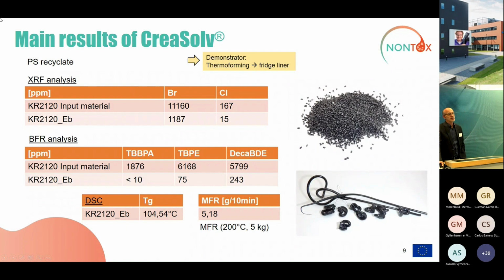Same is true for polystyrene. Again, here bromine and chlorine levels. So you see the input and the output. You see again that specific BFR analysis clearly indicates that the substances of concern are significantly reduced and below any levels of concern. Again, glass transition is in the typical range, and the MFR is also in a good range, indicating that the material has not degraded and can be reused. Color-wise, the same is valid as before.